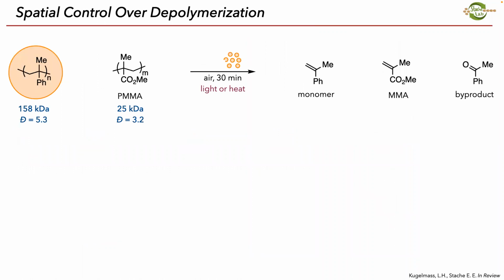And then lastly, just to show one of the huge advantages of using photothermal catalysis over standard bulk thermolysis, is getting spatial control over depolymerization. If we take our polymer with the nanomaterial in the presence of plexiglass, or polymethyl methacrylate, under our conditions of visible light, we only see formation of the poly-alpha-methylstyrene monomer. This 1%, and I should really put this over here, actually came with the material. So there's a little bit of monomer in there. That was not formed under our conditions. It came with the polymer. And we see less than 1% of acetophenone byproduct.